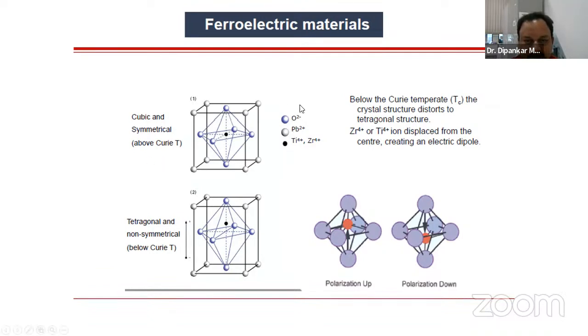So take lead zirconium titanate, PZT. How does it work? In the case of, let's say, a cubic system, they are symmetric above the Curie transition temperature. There is a temperature known as the Curie temperature, below which the ferroelectric materials work. If you go above the Curie temperature, then the ferroelectricity as well as the piezoelectricity will not work. If you buy a piezoelectric device, you can see the operating temperature range. You should work within 100 degrees, 50 degrees, 40 degrees, something like that. So this Curie transition temperature determines the operating temperature of the device. This is the temperature where the ferroelectric to paraelectric transition takes place.